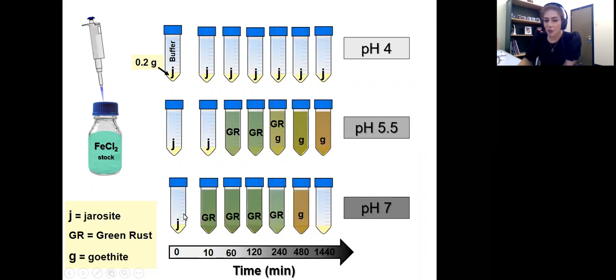So I added my iron 2 to this suspension at pH 7, and green rust formed in even less than 10 minutes of addition of my iron 2. And it was stable for some hours, up to about 8 hours, and then it completely transformed to goethite by the end of the experimental period. So the transformation of the iron 3 mineral was evident from my samples, and the effect of iron 2 concentration and pH was also confirmed.